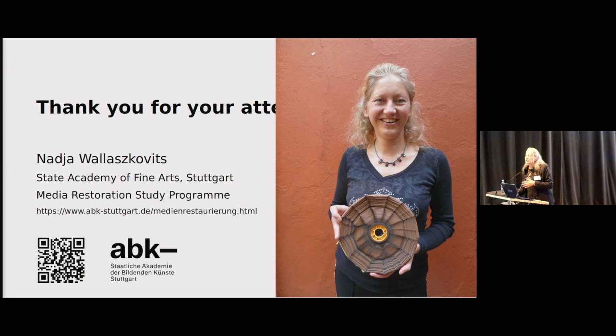So we have a very good knowledge about which plasticizers have been used because we have been doing lots of studies with ATR, with gas chromatography, but also non-destructive tests with solid phase microextraction, which is a technology where you have a small glass fiber inside the box and you can measure what is outgassing from, for example, a film roll under different conditions. You can, for example, heat it a little bit up and then measure what is outgassing. The fiber is taking on all these gases and then it's heated in the gas chromatograph and then you can have an analysis. And usually the older the material, the longer chains you find. Phosphate, diphenyl phosphate, triphenyl phosphate, DOP, and so on.